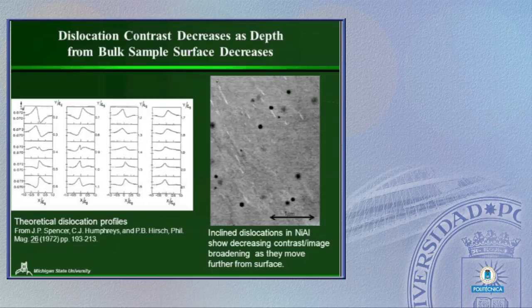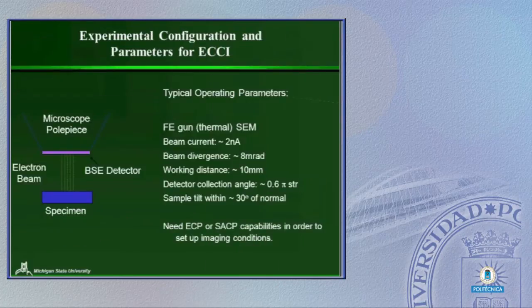Because if we were seeing all the dislocations through the depth of a bulk sample, we wouldn't be able to see anything. They would completely overlap and make it difficult to see. So this is a useful thing for us, but it also means that it's going to be a little bit more difficult for us to interpret the dislocations relative to how we're used to seeing them in TEM.